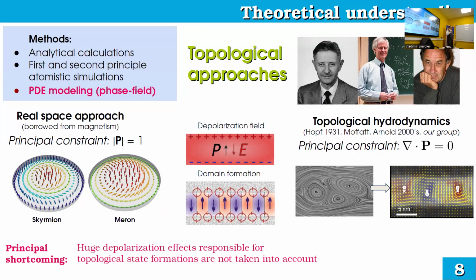Basically they destroy this configuration very quickly. So this constraint is for the bulk, but in the edge it is quite different. No, but basically you see it's a global topological constraint. So it means that, for example, on the surface, the vector of polarization should be tangential to the surface. But we will come to this and explain.